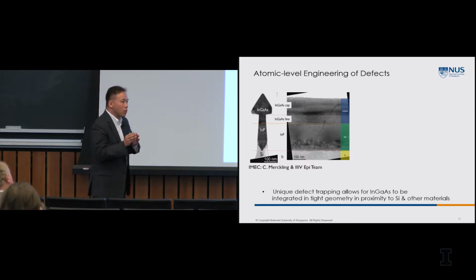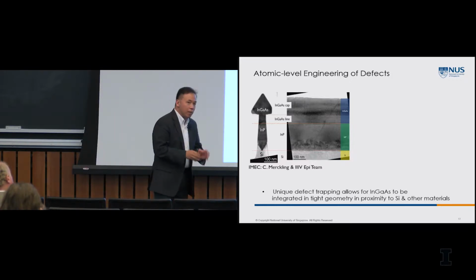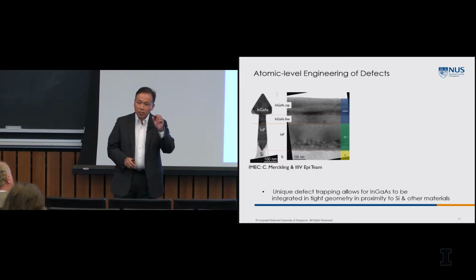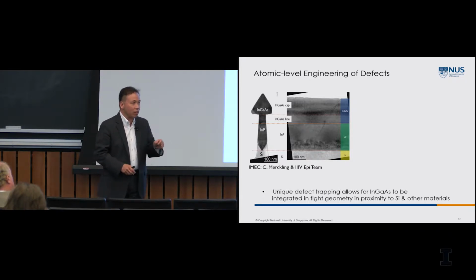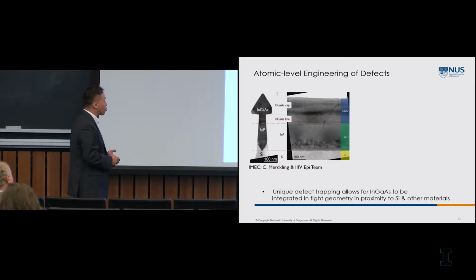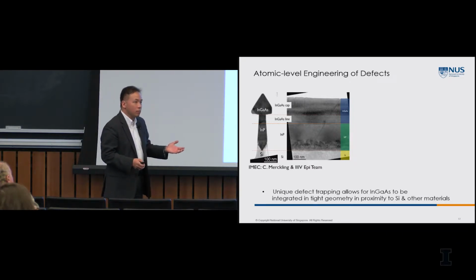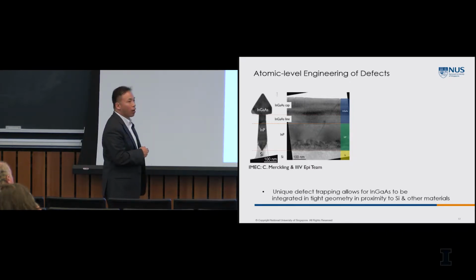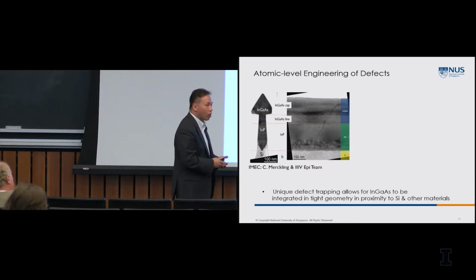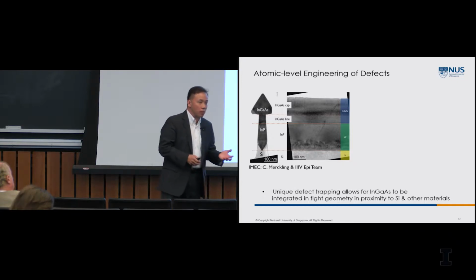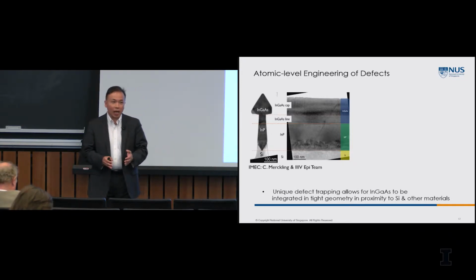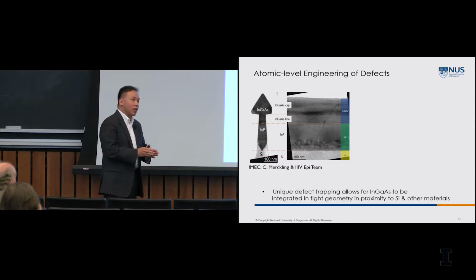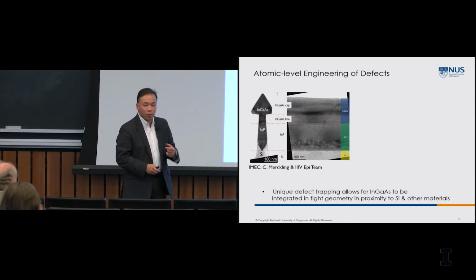How do you put a material with at least 8% lattice mismatch in the same volume as those tiny fins? That's the challenge that I worked on with the team at IMEC. The way you do it is you build a fin in silicon, and then you remove part of that fin, and then you regrow it with a III-V compound semiconductor, in this case indium phosphide. So basically, you just use the fin as a mold to put in new material.